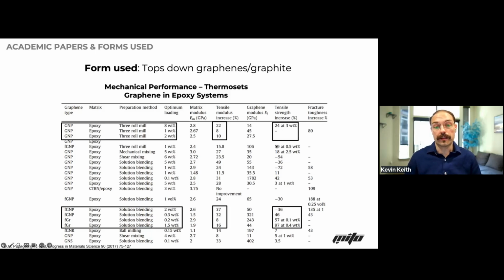So I really like this study because it was really showing everything side by side of how it really compared to these nanoplatelets, graphenes, and functionalized systems, that when you start adding the chemistries on top of it and knowing what to plug into the system, you actually start getting these huge increases at extremely low loadings.